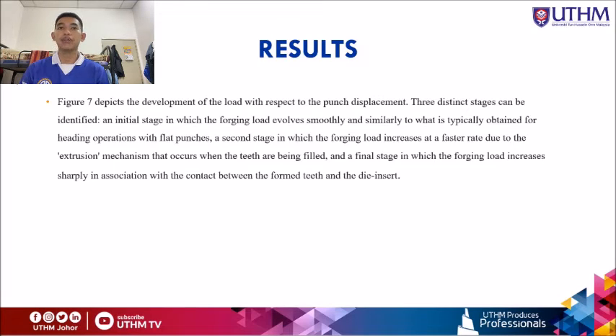Three distinct stages can be identified: an initial stage in which the forging load evolves smoothly, similar to what is typically obtained for heading operations with flat punches; a second stage in which the forging load increases at a faster rate due to the extrusion mechanism that occurs when the teeth are being filled; and a final stage in which the forging load increases sharply in association with the contact between the formed teeth and the die insert.